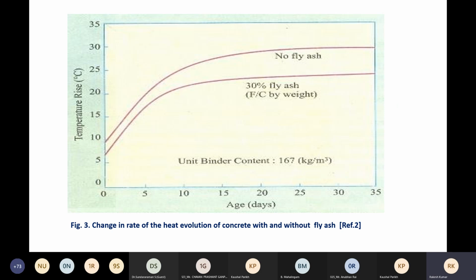Here you see temperature rise and age. On the upper side is no fly ash, and the second curve is 30% fly ash. In the concrete in which fly ash is not used, the temperature rises to around 30 degrees centigrade. But in the other concrete in which 30% fly ash is used, the temperature is around 20 degrees centigrade. It is available in the literature that in mass concrete we use certain pozzolanic materials so that the heat of hydration is reduced.